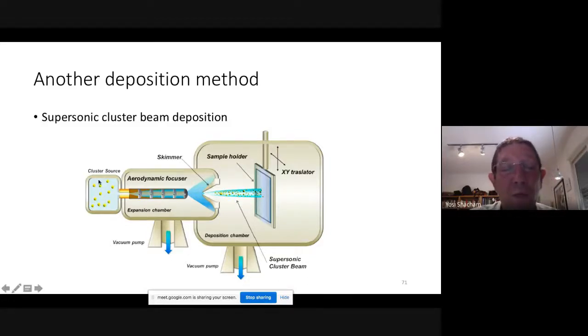We focus on biomedical devices, and the idea is you take a source which is called a cluster source, and you are generating nanoparticles of metals. And these nanoparticles can be 1 or 2 nanometers in size. You accelerate the nanoparticles, and you shoot them into your PDMS. Remember, PDMS is your flexible substrate, and you want to make the flexible device on the substrate. So you put gold into it.